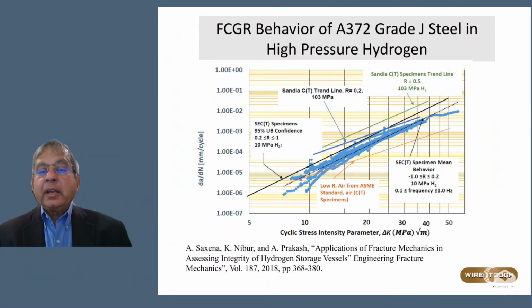We have done, and so has Sandia National Lab done, a lot of materials testing to document the fatigue crack growth behavior in pressure ranges from about 10 MPa to 100 MPa of hydrogen. And this has been done at various load ratios. The reason for doing it at various load ratios is that the service cycles can be partial unloading or full unloading of the pressure vessel. So depending on what the minimum pressure is, the load ratio or the stress ratio that the vessel is subjected to does change. And these test results range from R equal to 0.5 to R equal to -1, which is for wire-wound cylinders, as we will see later.